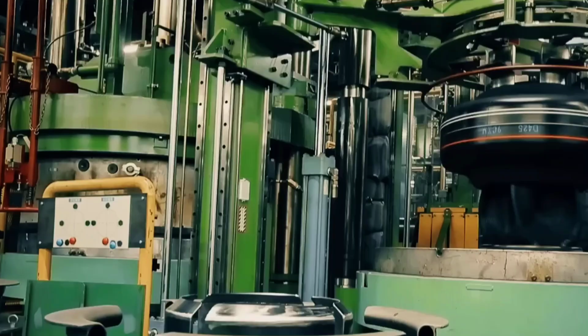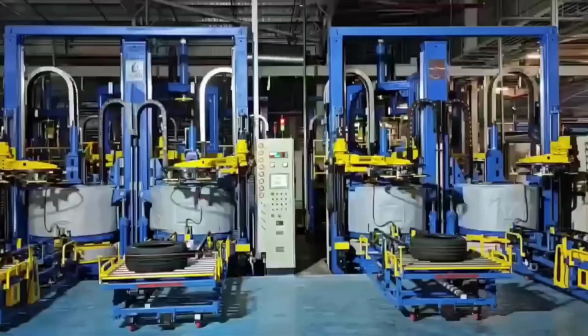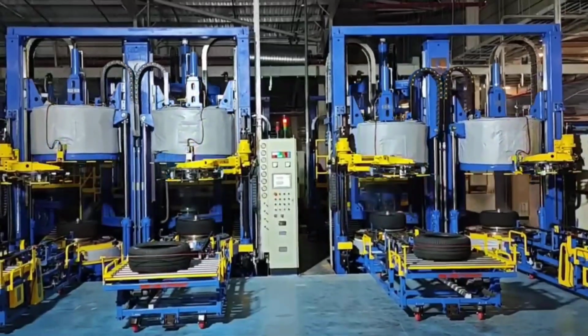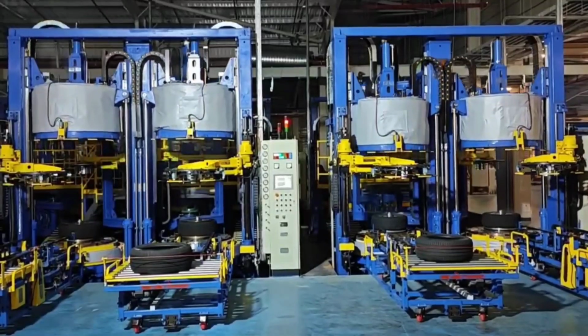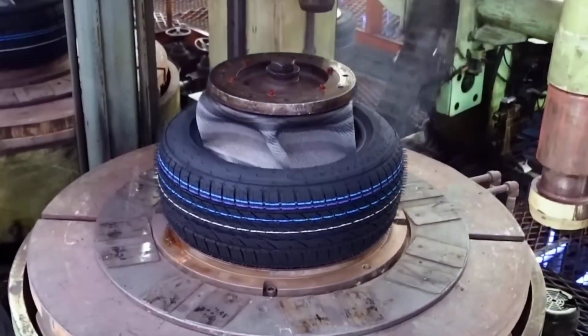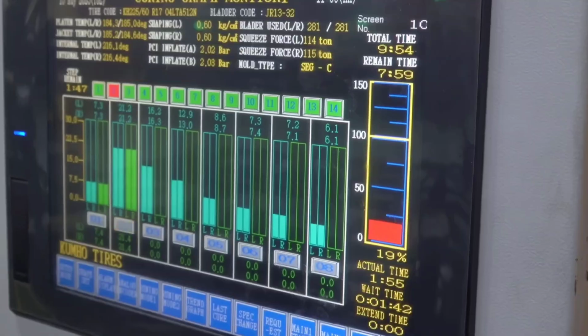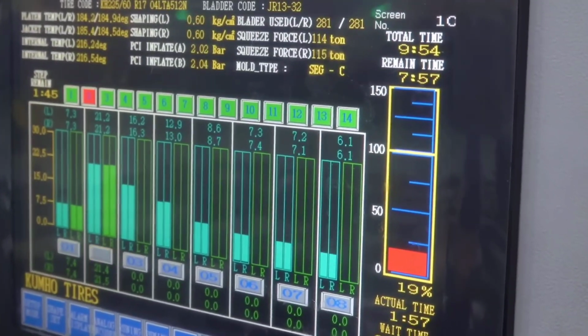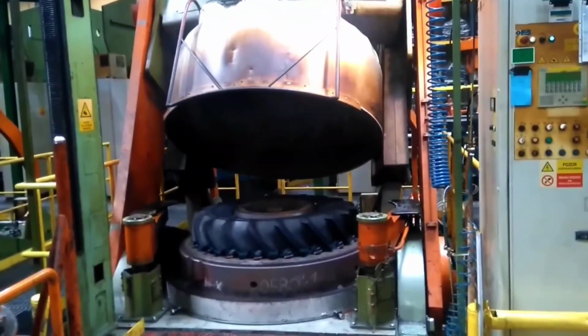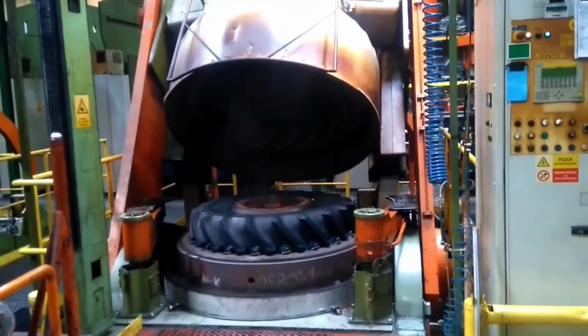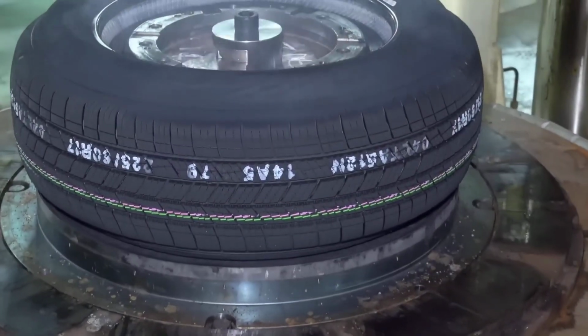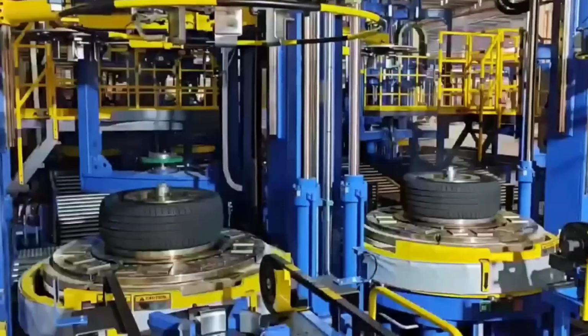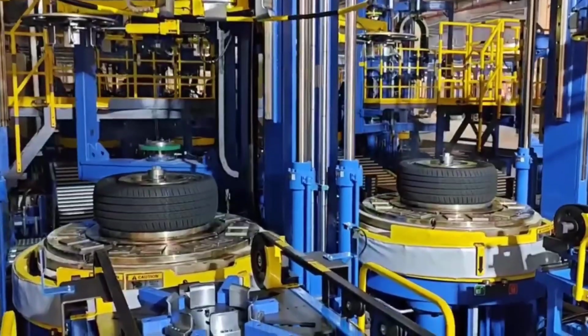At the same time, compressed air or superheated fluid is pumped into a flexible bladder inside the tire, creating pressure that pushes outward. Under this force, the softened rubber expands and presses firmly into every fine groove of the mold, forming the final shape of the tread. The vulcanization process lasts between 10 and 15 minutes, depending on the tire's size and type.